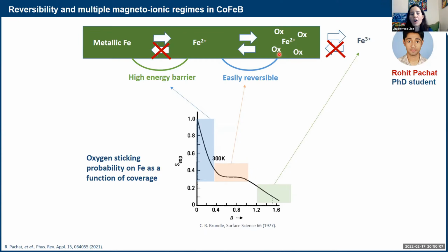So those oxygens are far easier to remove. And I put Ox here because we don't really know what this is, if it's an OH or an O2-. It's some oxygen species. These are far easier to remove from the sphere of the iron 2+ than a proper oxide bound to the iron. Here you have to go from 2+ to metallic iron. This takes a lot more energy than getting one of these oxygens away from the 2+, while the iron 2+ still keeps its oxidation number.